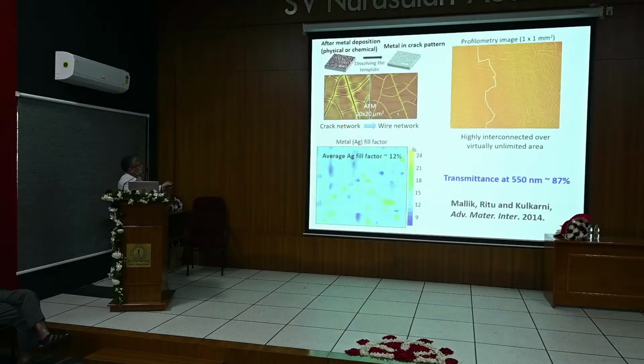So take a piece of glass and do the sacrificial coating, allow it to crack. These are spontaneously formed cracks. And then shower metal on top. In this case, we showered gold. This is a model study, okay? And so this is a fine set of cracks here. This is an atomic force microscopy image.